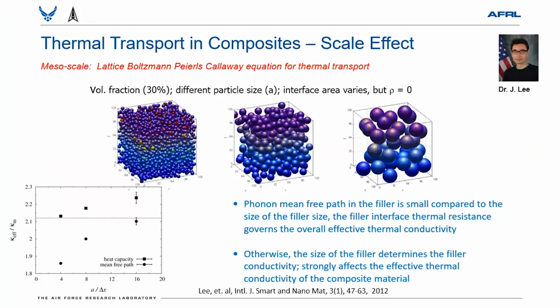Another point I'd like to make is that as we go from small scale to bigger scale, the size of the individual material constituents plays a role. So how do you say what the design factor is? In the case of thermal, if the material is very pristine, then the phonon mean free path will be very large. When it's defective, the phonon mean free path is small. If the phonon mean free path is small compared to the size of the domain, then the interface plays a role. Whereas if the phonon mean free path is large, meaning pristine material, then the interface will not be an issue. Those are the design rules we can follow.